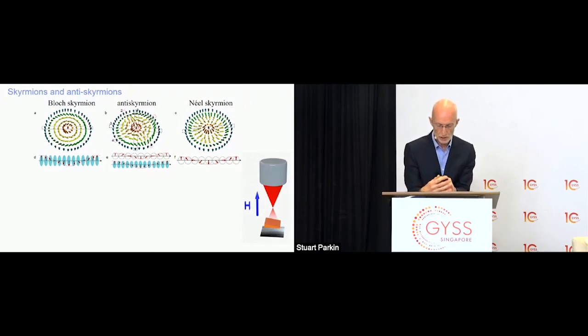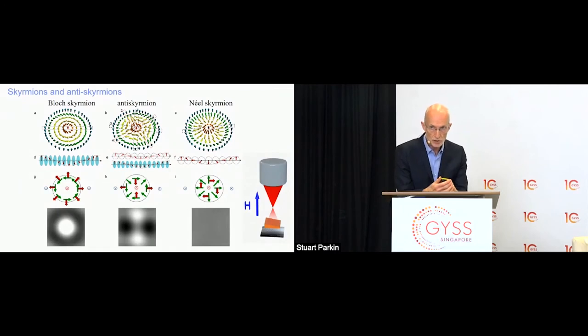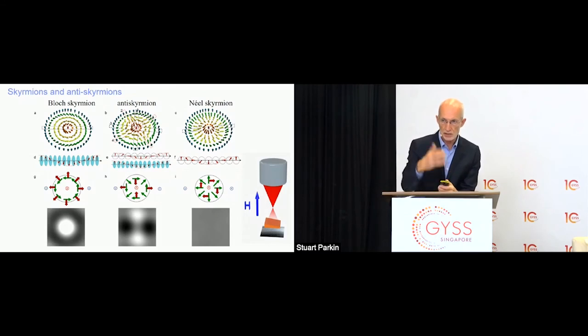When the high energy electrons, 300,000 volt electrons, are passed through this lamella, they will be subject to Lorentz forces from the magnetic component of the magnetization in the plane of the film. And this means that if we have a Bloch skyrmion, then in the Lorentz microscope, this will look like this, as you can see here, this white blob of increased electron intensity. On the other hand, the Néel skyrmion is invisible because the Lorentz forces cause the electrons to be rotated around the circumference of the object. So there's no change in the intensity.